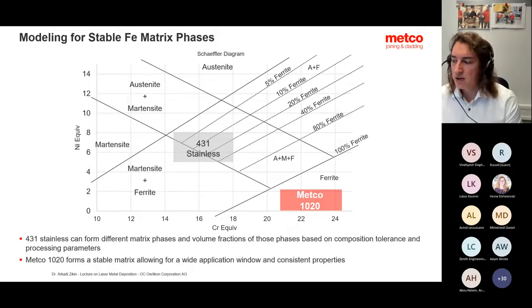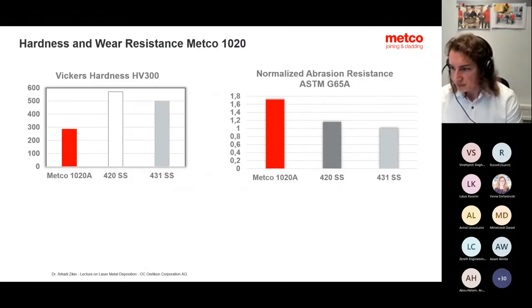design an alloy which, no matter how you set your deposition process, maintains a ferritic environment, and at the same time, the wear performance is done not by converting chrome to chromium carbides, it's done by precipitated, hardened, fine-grained particles of, for example, titanium or niobium carbides, which are formed on grain boundaries and which ensure you get your desired wear protection.